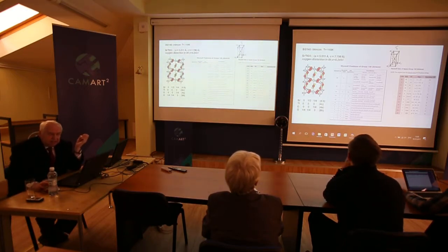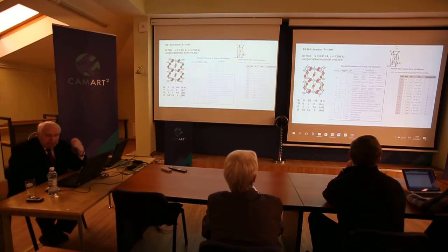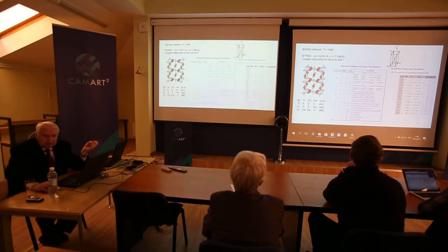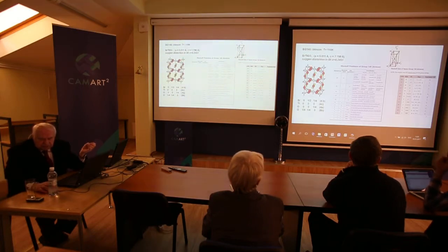In any case, as you know, especially those who work experimentally, the space group depends on the temperature. And in this case, the low temperature phase gives you a different space group, different Wyckoff position occupations, and what is interesting is that in this case you have no equivalent description of this structure. You see that in this list of Wyckoff positions there are no equivalent positions. So there is only one possibility.